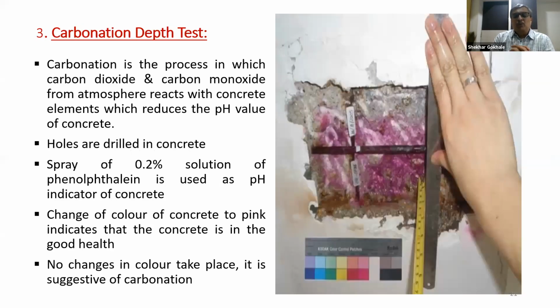Then the carbonation depth test. Carbonation I have already explained, where there is a reduction in the pH value of the concrete. Holes are drilled in the concrete, and phenolphthalein solution is spread in that hole, and there is a color change. Based on the color change, we can make out up to what depth the carbonation has gone inside. So if the cover concrete of the column is say 40 mm, and the carbonation depth as per this color change is say 25 mm, that means the carbonation has reached a depth of 25 mm, but has not reached up to the reinforcement level, since the cover is 40 mm. So there is some more time before reinforcement corrosion begins. That we can make out from the carbonation depth test.